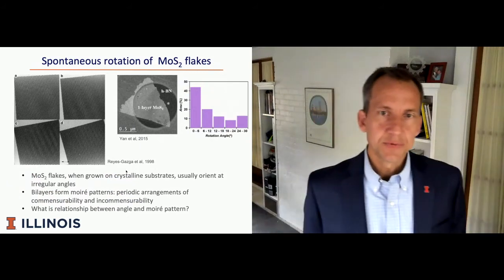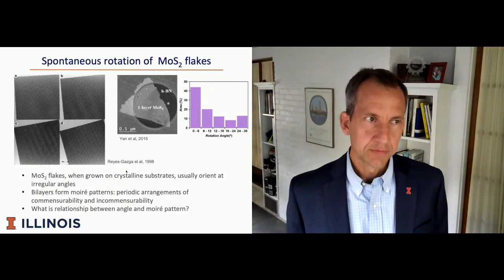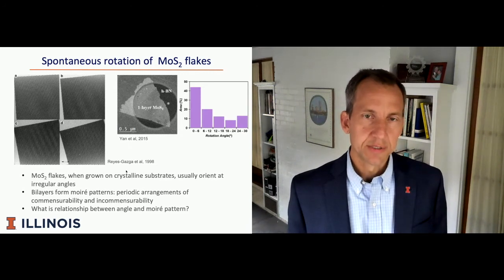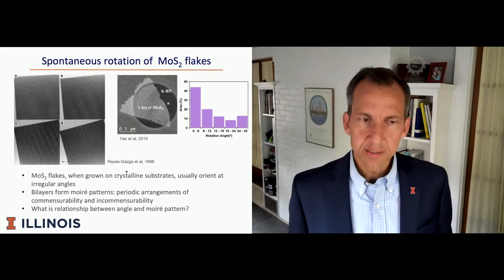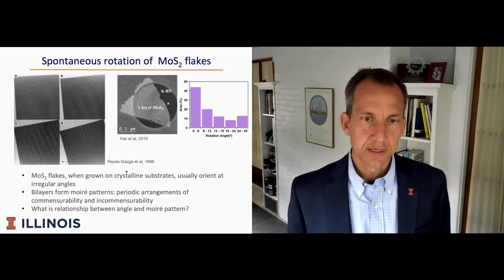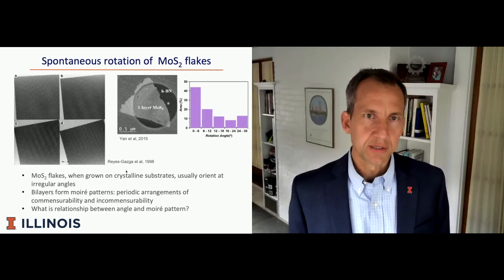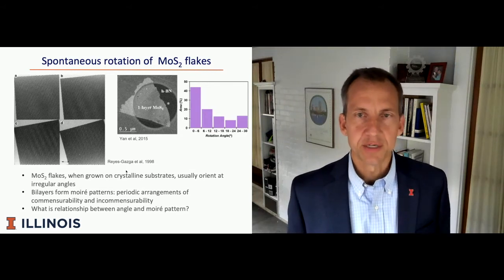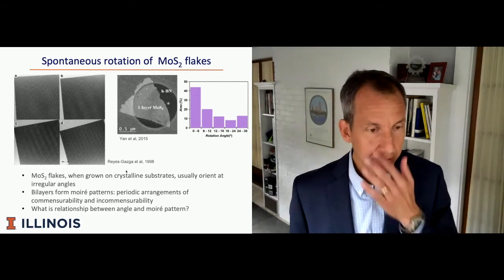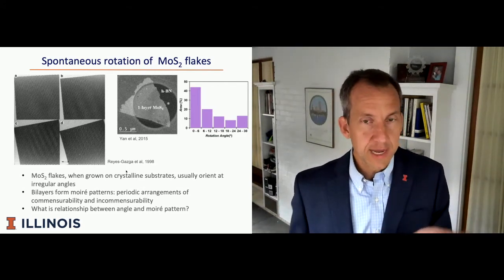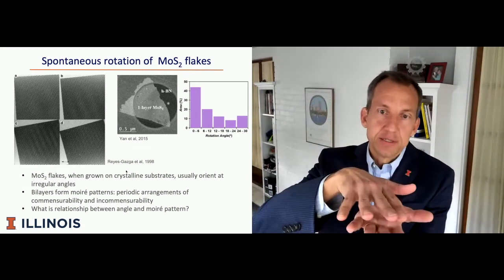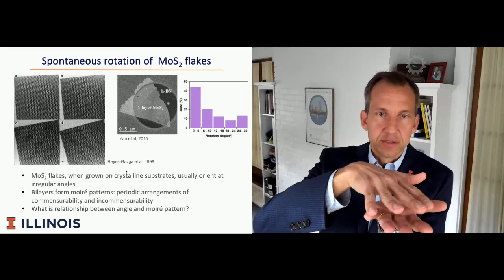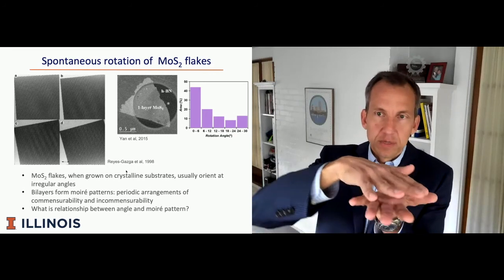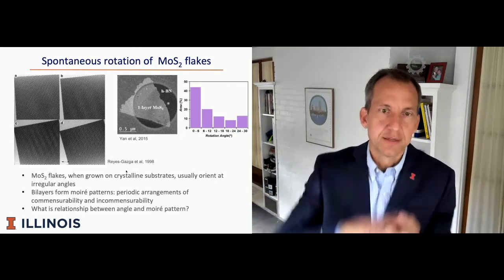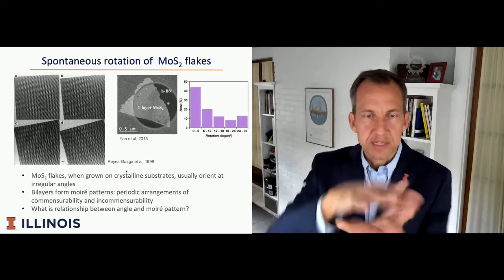Now, the case of MoS2 homostructures or stacked bilayers is interesting, and it's not unique though. There are other systems that have similar behavior, but in particular, I want to focus on the observation that in these stacked structures, one observes in some cases spontaneous rotation of the flakes. And when I say spontaneous rotation, I mean when a stacked structure is made with a particular alignment, it is sometimes, in fact, often observed that a small flake will spontaneously or autonomously, if you like, rotate to off perfect stacking.